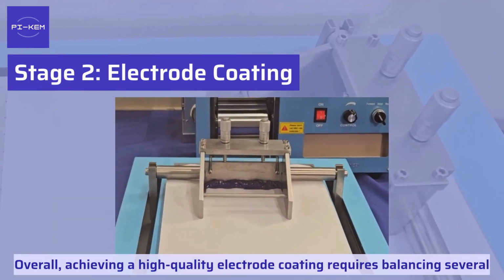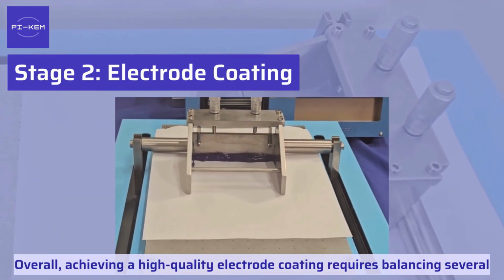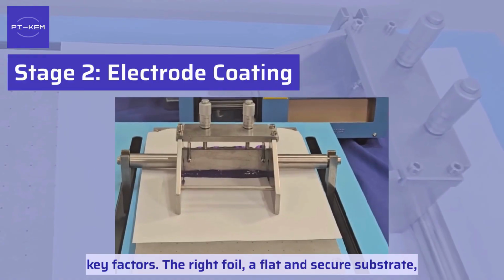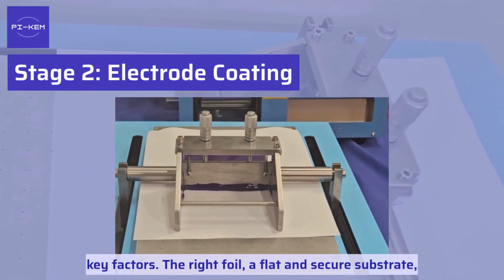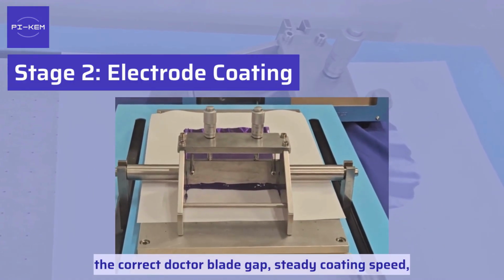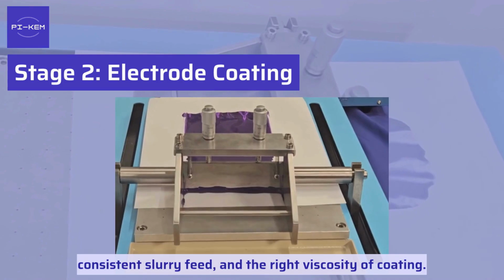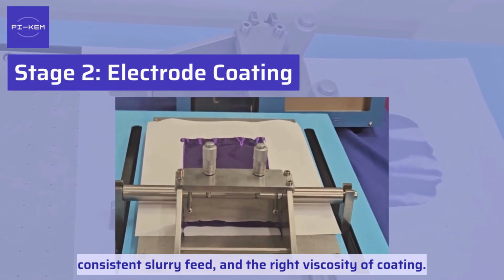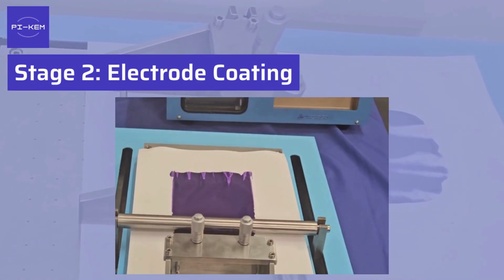Overall, achieving a high-quality electrode coating requires balancing several key factors: the right foil, a flat and secure substrate, the correct doctor blade gap, steady coating speed, consistent slurry feed, and the right viscosity of coating.